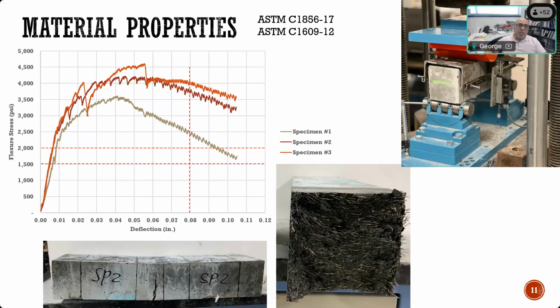So you look at this material, you evaluate it with respect to the cracking stress, which is the first line here. According to PCI, it requires to be more than 1500 psi, and the peak should be higher than 2000 psi. And also looking at the residual stress at L over 150 of the span, which is 0.08 inches. So it requires this to be at least 75% of the peak. And as you can see here, all the specimens we tested for the mix developed in Nebraska meet these requirements quite well.